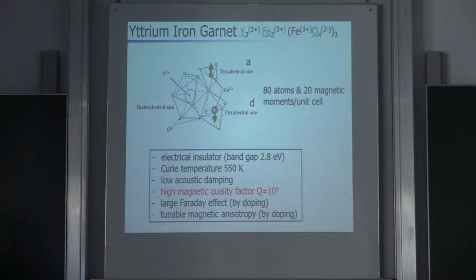So the ions are hidden within these cages here. Now, the magnetic ions are strongly coupled antiferromagnetically via superexchange via the oxygen ions. So that means the tetrahedral and octahedral site magnetic moment is in the opposite direction. But it's not an antiferromagnet, it's a ferrimagnet, because we have more of the tetrahedral sites than the octahedral sites. And I think there's one iron moment basically per chemical unit.